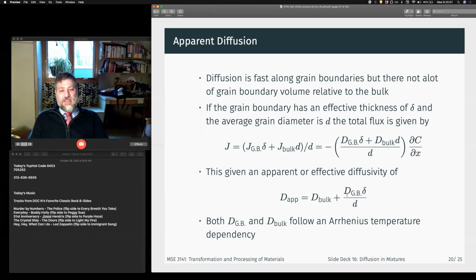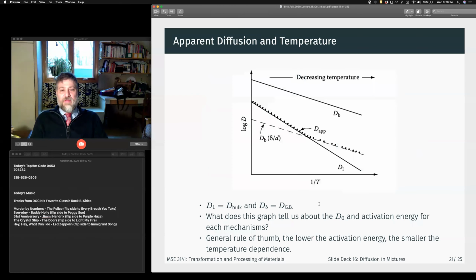Both of these are going to have a temperature dependence that's Arrhenius in the same way, right? They're going to have potentially different activation energies, but they're both going to be exponential with temperature. But this bulk term has a much higher cross-sectional area, much larger area for flux to go through than the grain boundary term.